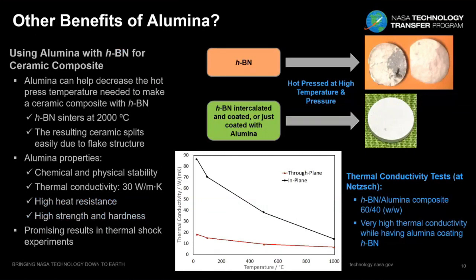What are the other benefits of modifying the hexagonal boron nitride? In this case, with alumina, well, hBN sinters at a very high temperature, 2000 degrees Celsius. And to make a puck is very difficult because our hot press limit is 2000 degrees Celsius. So we cannot use it at that high temperature.